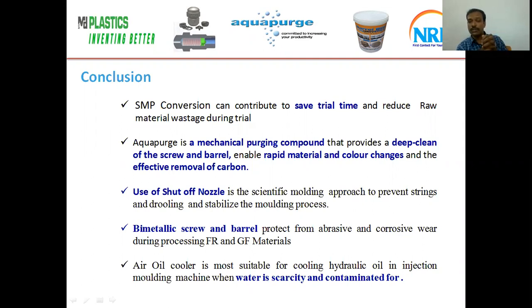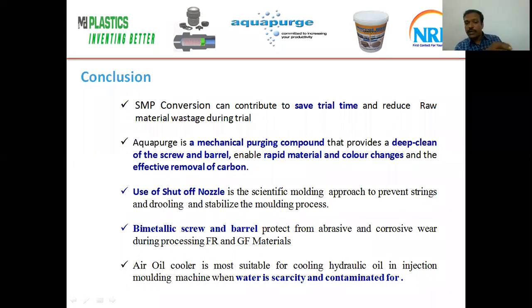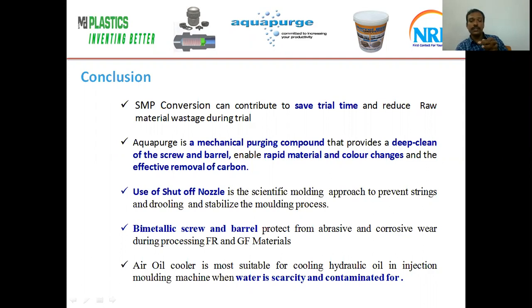Use a shut-off nozzle to prevent drooling and stringing. It also stabilizes the molding process for consistency. Bimetallic screw and barrel protect from abrasive and corrosive wear while processing FR and glass-filled materials. The air oil cooler is the most suitable cooling for the oil in an injection molding machine instead of a heat exchanger when water is scarce and contaminated.